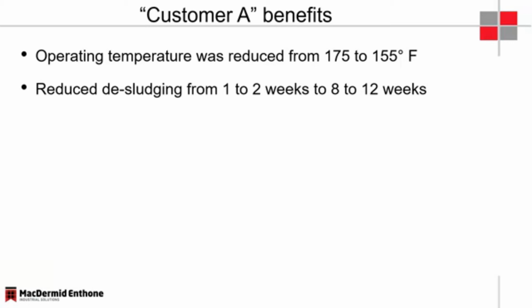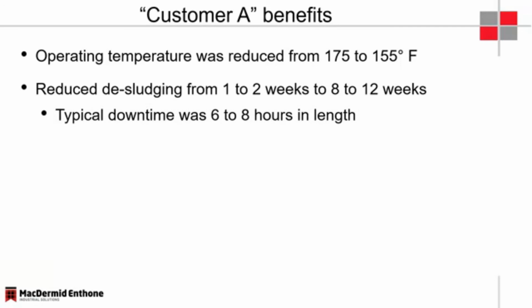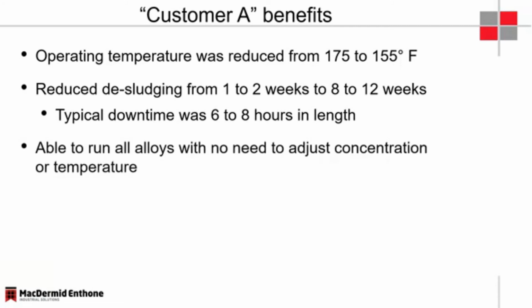They've also been able to reduce their desludging frequency. So again, they had to take their tanks down typically every 1 to 2 weeks to desludge. We have widened that window to about every 8 to 12 weeks. And when you multiply that by the typical downtime of 6 to 8 hours, that translates into a lot of additional productive time over the course of the year.